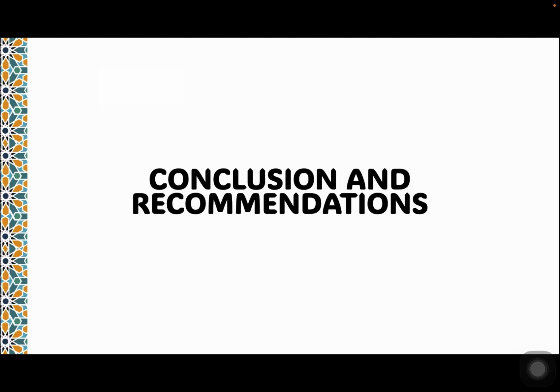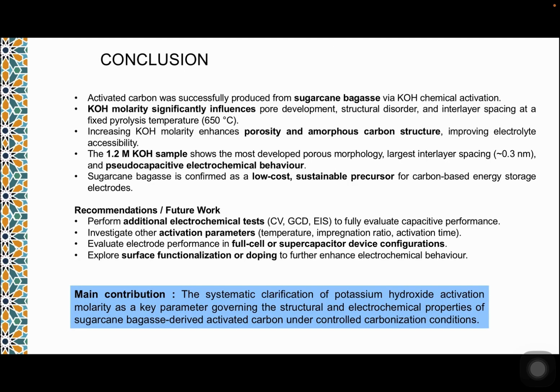Last but not least, the conclusion and recommendations. From this work, we can conclude that the activated carbon was successfully produced from sugarcane bagasse via KOH chemical activation. From here, we also found that KOH molarity significantly influences pore development, structural disorder, and interlayer spacing at a fixed pyrolysis temperature. Increasing KOH molarity enhances porosity and amorphous carbon structure, improving electrolyte accessibility.